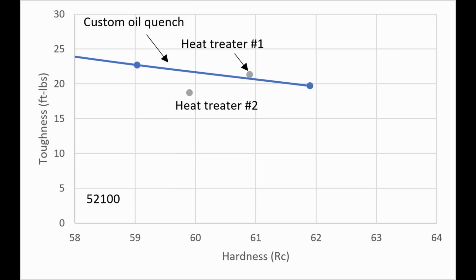However, I have examples for 52100 where they were oil quenched in a commercial heat treating facility. And I have that compared with a custom oil quench performed by knife maker Warren Kryko. Because the oil quench is similar, whether it's in a custom shop or in a commercial heat treater, the quench rate is also similar. And so the toughness-hardness balance of the commercial heat-treated 52100 is similar to the custom oil quench performed by a knife maker in their small shop.